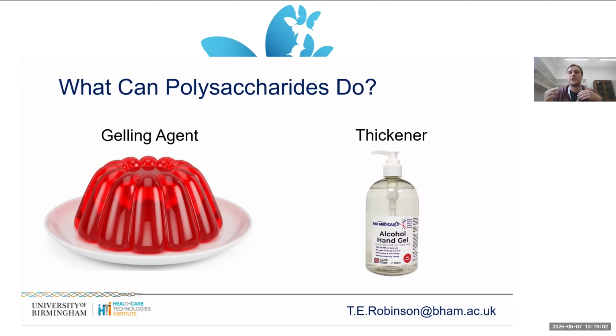So actually that's what these molecules do when I talk about structuring water. Having these at 1 part in 100 or normally less, so less than 1% polysaccharide, you can completely change the material properties of something that's mainly water. As an aside, if anyone's ever wondered, when they hear our bodies are made of 70% water, how can that be? Because I don't feel myself sloshing around. This is why. Tiny, tiny amounts of long polymer molecules like polysaccharides can create a lot of structure out of water.